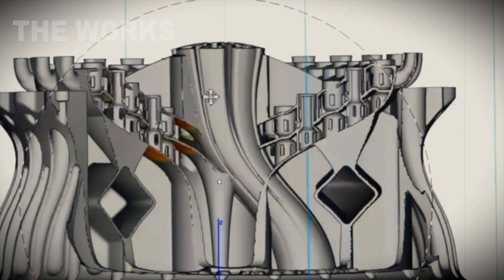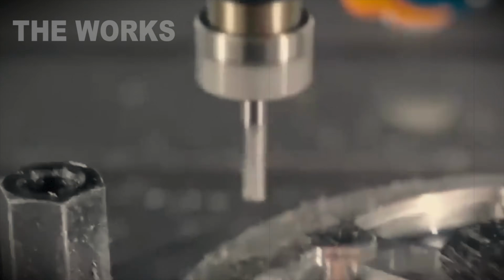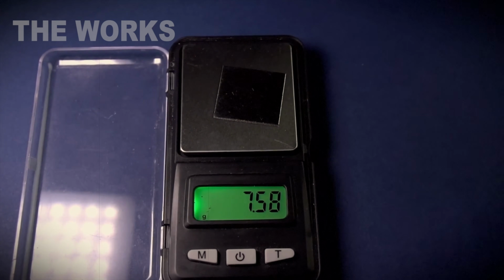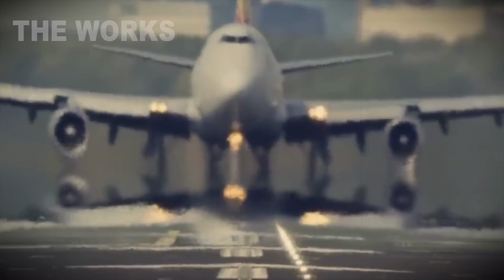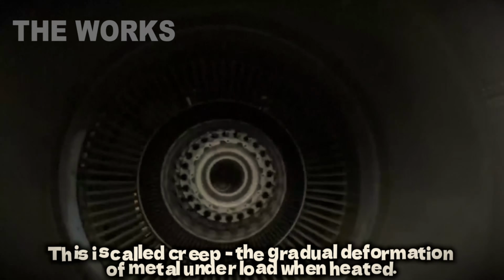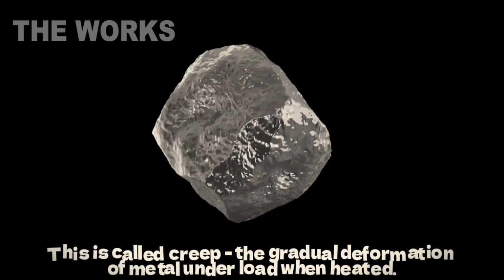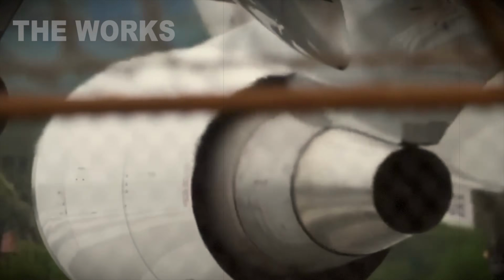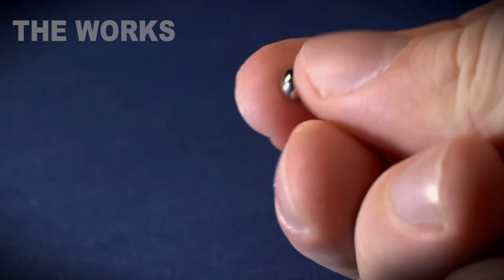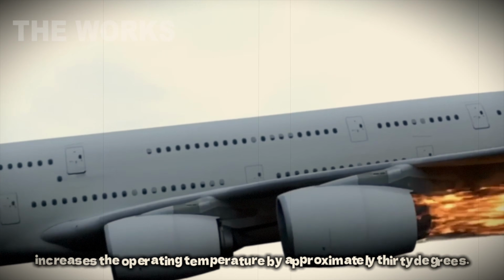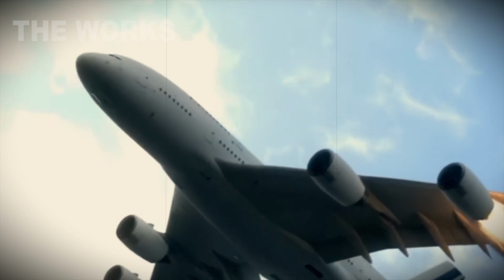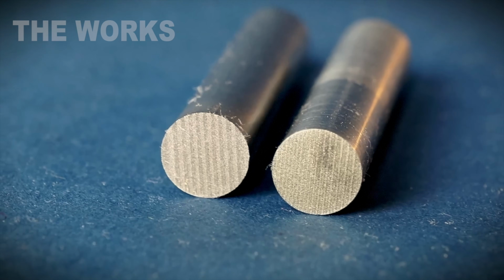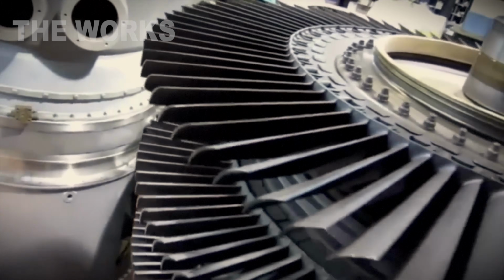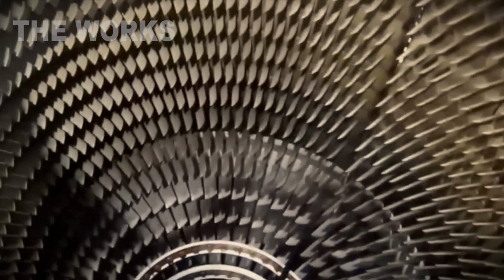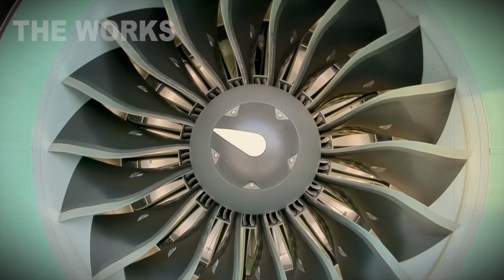Rhenium does something remarkable. It dissolves into the nickel matrix of a superalloy and blocks defect movement in the crystal structure at high temperatures. This is called creep, the gradual deformation of metal under load when heated. All metals creep, but rhenium slows this process down dramatically. Adding just 3% rhenium to a nickel superalloy raises the operating temperature by about 54 degrees Fahrenheit. Doesn't sound like much? But in jet engines, every 18 degrees of additional temperature yields roughly 1% more efficiency. And efficiency means fuel consumption, flight range, airline economics.